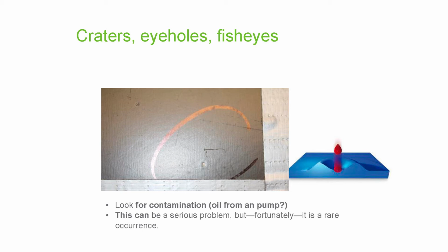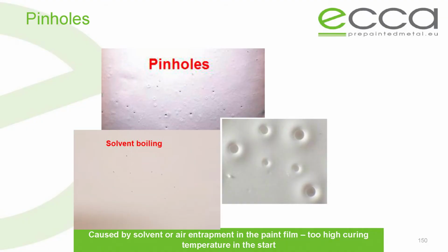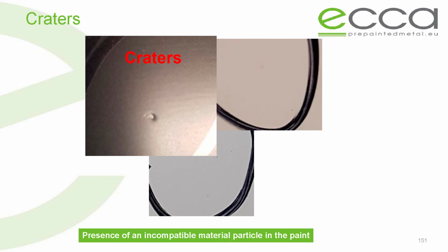Surface tension differences, however, are the explanation for why you get craters and fisheyes. In that particular case, even though it's probably not a big problem on a coil line, that's where you really need to have a surface tension modifier to try to eliminate the differential that occurs. And we've got plenty of examples of holes in paint.